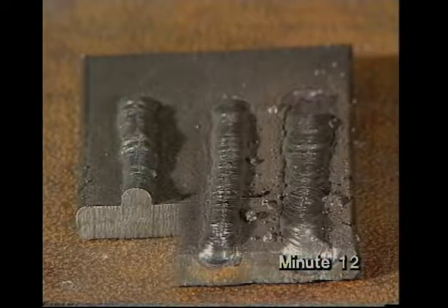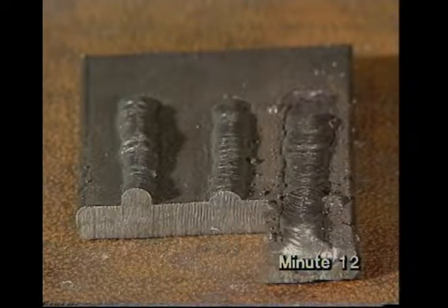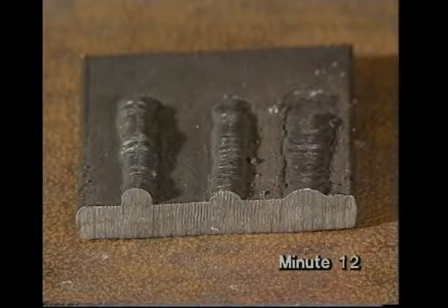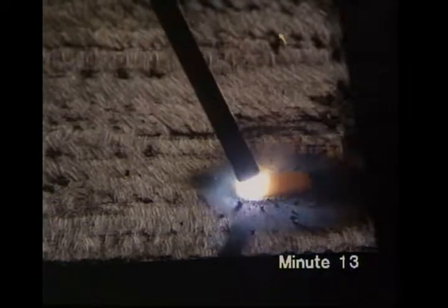With low current, the weld bead is cold. It hasn't melted into the plate. With normal current, it is smooth and rounded. With high current, it's wide, flat, and spattery. If you let the arc get too long, it will go out, as well as increasing spatter and making a faulty weld. And if it gets too short, the result's obvious.